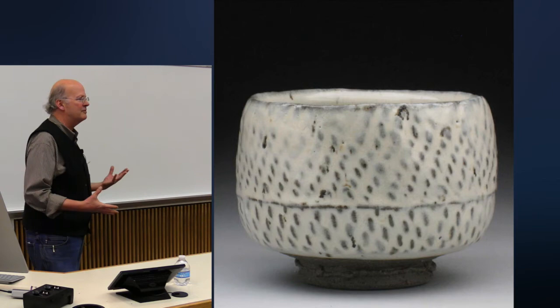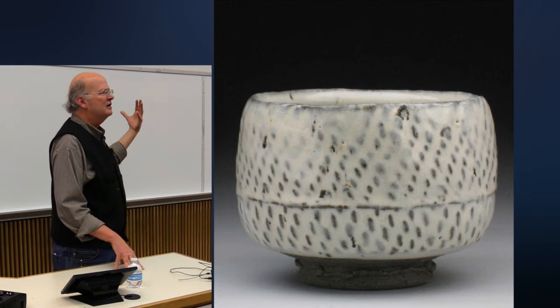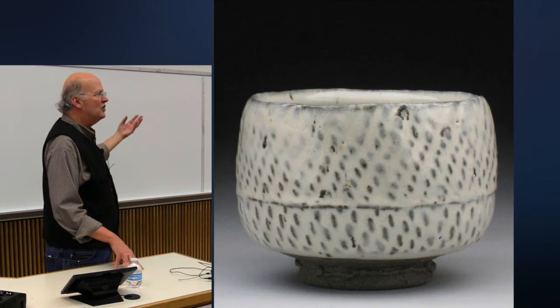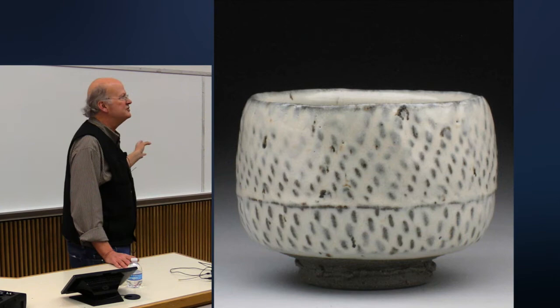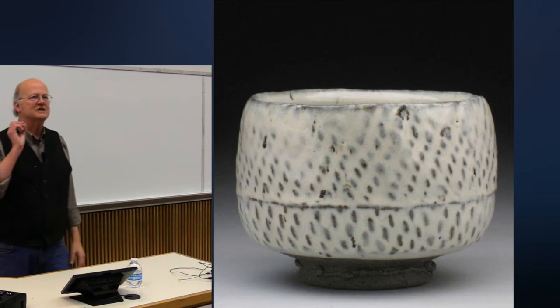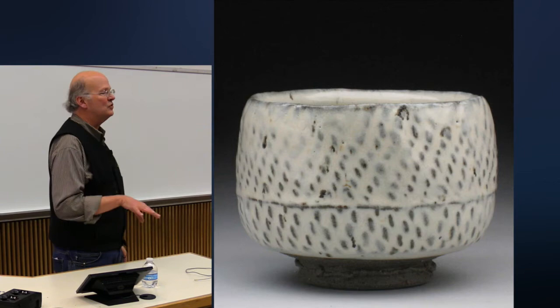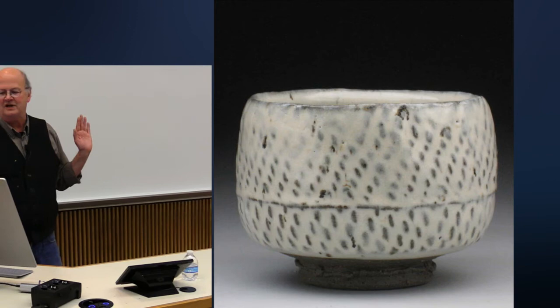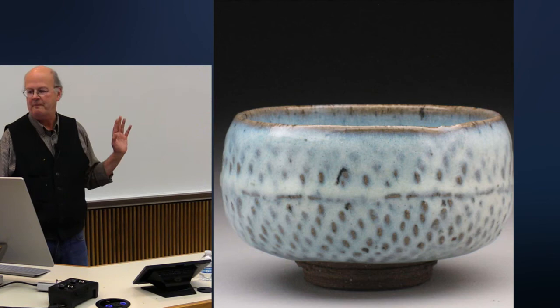And this is a really simple glaze that's based on straw ash or rice hull ash that happens to be very high in silica, and feldspar. Feldspar is another very commonly occurring mineral. And so that feldspar and the straw ash make a glaze that looks like that. But what's interesting in this case is changing the atmosphere of the kiln as it fires and cools changes the nature of the glaze. And there are lots of examples and an infinite number of variations that are possible on this.